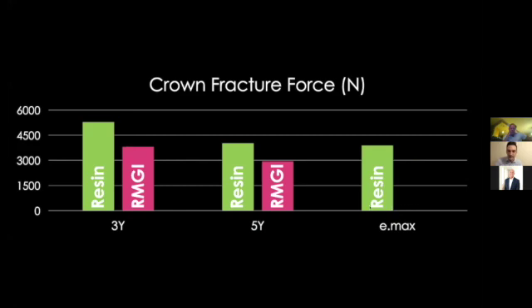Another thing that was interesting between the Emax and the 5Y zirconia was that they had the same strength once the two things were bonded. But you could see the 5Y zirconia, when it was conventionally cemented with RMGI, survived the test, and it was a lower strength, but it did survive the test, unlike the Emax material at that thickness. So that tells me two things. First of all, once they're bonded, they're going to have a pretty similar strength.